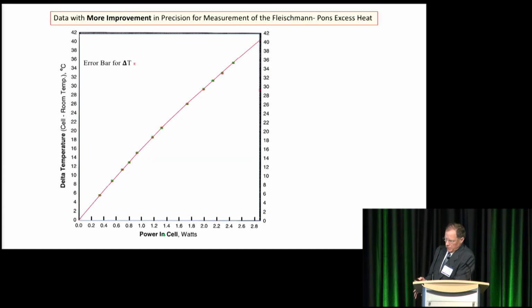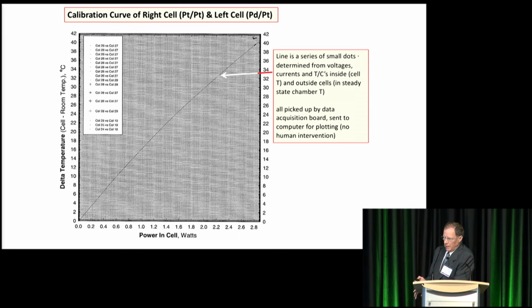If you think this is good, this is my data, and this data is not a line that I drew through the data. This is just a series of dots that were taken by the data acquisition card, put in an Excel file, and plotted automatically on the curve. And to get a new data point, you just move the electrolysis current up a little bit, or the electromigration current up a little bit to a new set point, let it come to steady state and acquire a new data set.